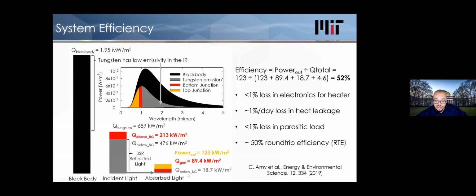There's heat generation, there's below band gap absorption. We've also modeled the convection. Convection is small, but not negligible. That's this other 4.6 kilowatts per square meter. And so you take the 123, divide by what you're getting out, 123 plus Qgen plus the below band gap absorption and the convective losses. And this still comes out to about 52%, all right?